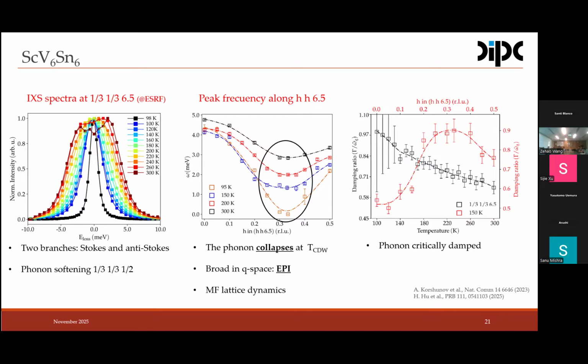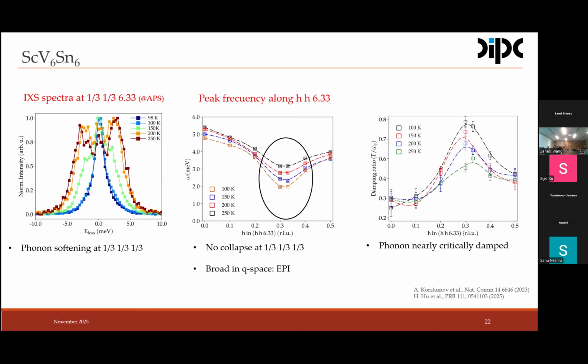Yeah, so as you recall, we actually can plot the momentum and temperature dependence of the linewidth broadening and the damping ratio. We actually see how the phonon approaches the critically damped value, which tells us about the freezing of a soft mode close to a phase transition. But as you recall, the charge order phase transition happens at L 1/3, not L 1/2. So then if we track the temperature dependence of the L 1/3 peak, the phonon Stokes and anti-Stokes, instead of hardening, which one would expect if we are not dealing with a phase transition driven by phonons, the phonon actually softens.